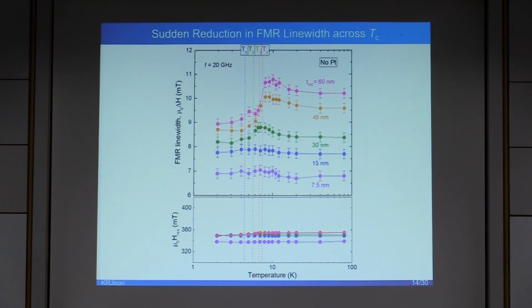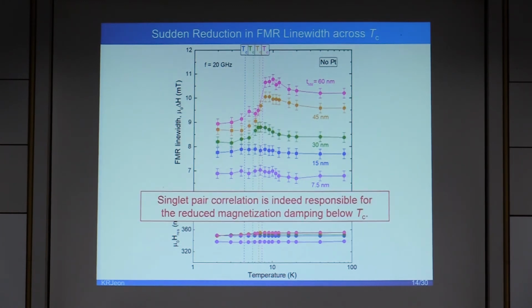For the temperature dependence of resonance magnetic field, regardless of the niobium thickness, it decreases very weakly by less than 3%, implying that the effective saturation magnetization is almost independent of either niobium thickness or Tc. This indicates that the superconducting correlation is indeed responsible for the reduced magnetization damping below Tc and thereby the suppressed flow of spin current.